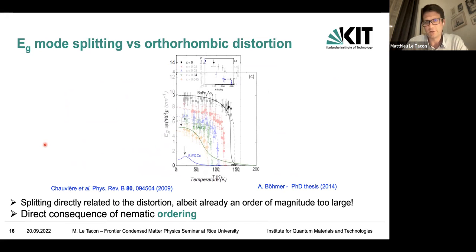Now, again, the splitting that they see compared to the distortion is about an order of magnitude too large. And back in 2009, I don't think there was already a lot of discussion about nematicity, but in the end, what it means is that this whole splitting is enhanced by the nematic ordering. So at least this is how it's understood now. Nevertheless, my first thought was, okay, there is a splitting which is at least an order of magnitude smaller in the nickelate.